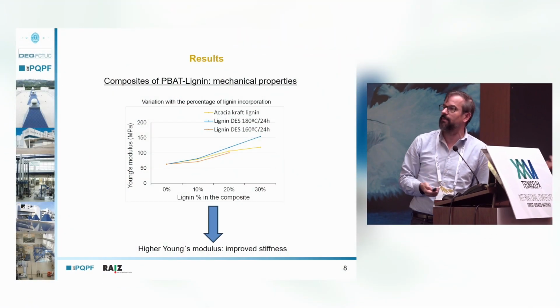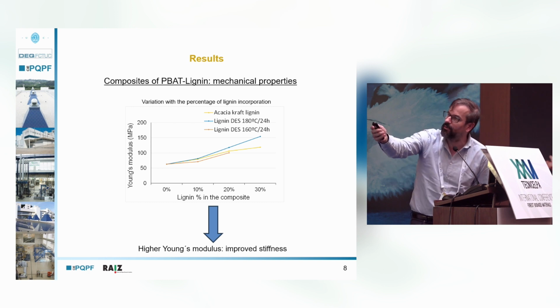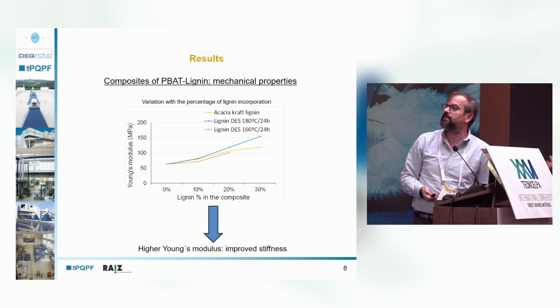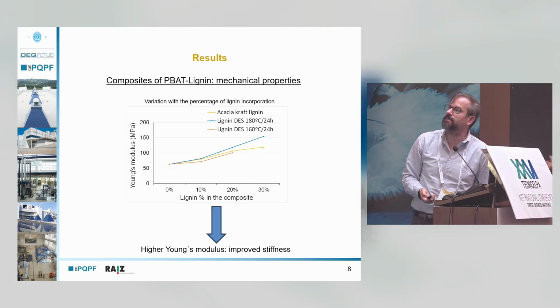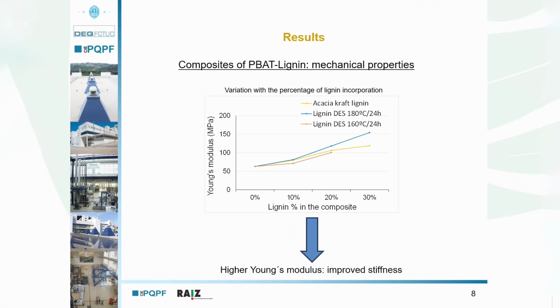We can see that stiffness is improved. The Young's modulus for PBAT alone is around 60, 70 megapascal, and for mixtures with 30% of lignin, we have Young's modulus up to 150 megapascal. Although the best results were obtained with lignin extracted with eutectic solvent, the result with acacia kraft lignin is also good. So it can also be an interesting option.